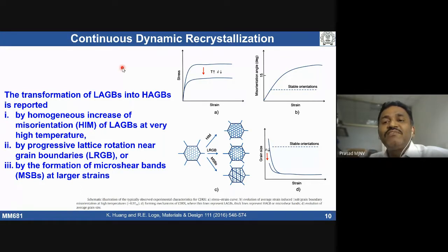No, sir. In high stacking fault materials there's no driving force left, because recovery is the first step and can happen very easily, so dislocation density has come down. In case of low stacking fault materials, recovery is very difficult. The difficulty of cross slip increases with decreasing stacking fault energy. That means you can store a large amount of dislocations in low stacking fault materials. Most of the time, more dislocations are stored near the boundaries, which are high energy areas. Now we have a driving force for recrystallization to happen.